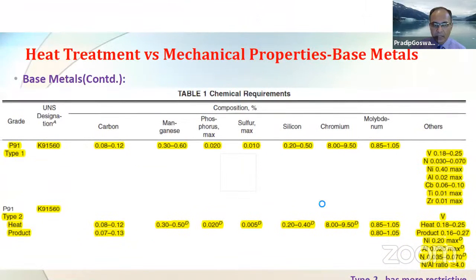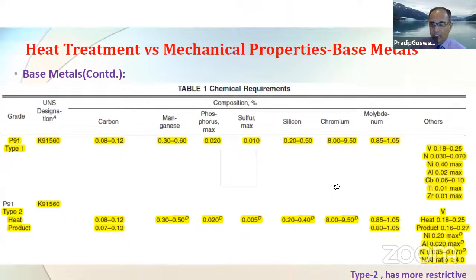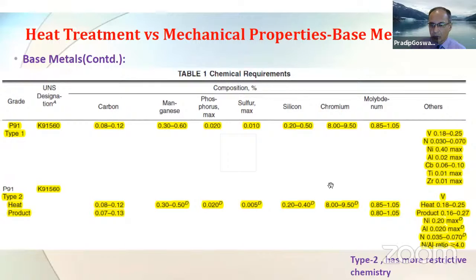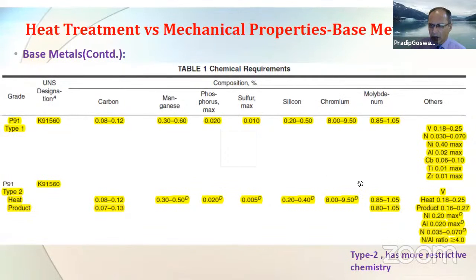So here is a typical chemistry of type 1 and type 2. The difference between type 1 and type 2, there are some certain minor differences with respect to chemistry also. When you see the normal alloying elements, carbon, manganese, phosphorus, silicon, chromium, molybdenum, they're almost back to back. They're almost the same.